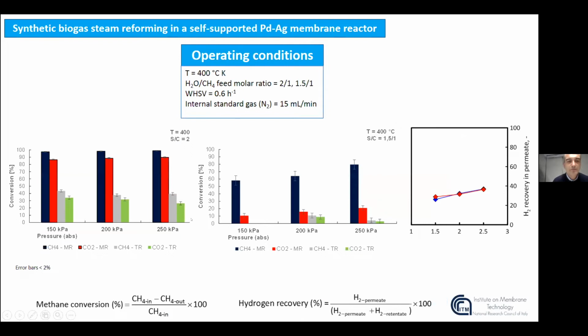Regarding the performance, in this graph on the left, it's possible to observe the conversion of methane as a function of the reaction pressure increase. And in blue color, it's possible to observe the conversion of methane in the membrane reactor at 400 Celsius degrees and stoichiometric feed molar ratio condition. The conversion is almost complete, and the higher the pressure, the slightly higher is the conversion of methane.